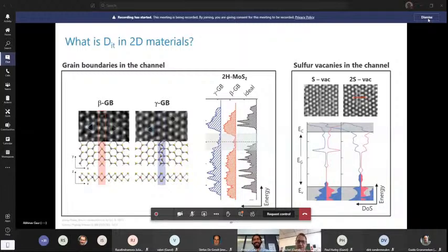Okay, all right. I was just wondering if you also tried to correlate, or you did also measurements on devices to see if there were some correlations possible between your findings and the transistor characteristics. In general, there is a good correlation in mobility, because we can calculate mobility from both DC IV measurements as well as our AC measurements, right? So there's a good correlation. So we can say based on that the mobility is between 1 to 10 or 1 to 20. Yes. It's pretty consistent.